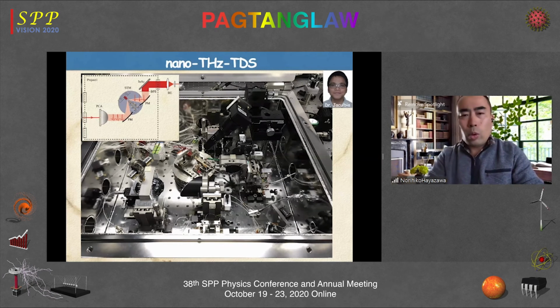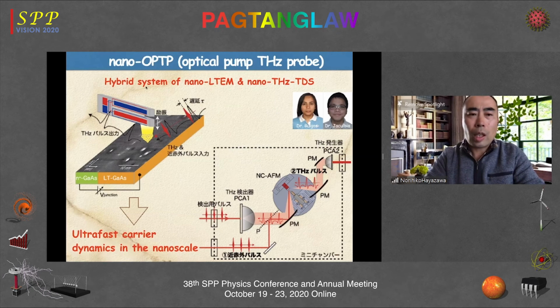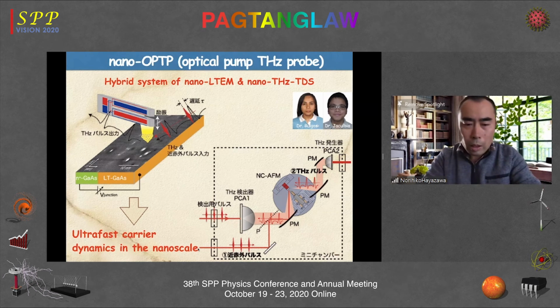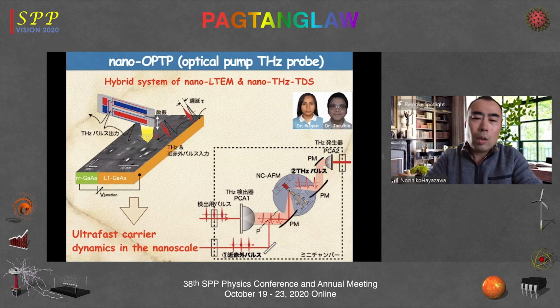And in fact, what we want to do is to combine these two systems. This is a kind of hybrid system of nano-LTEM and nano-terahertz time domain spectroscopy, called the nanoscale optical pump terahertz probe microscope. Briefly about this system, the near infrared laser pulse is introduced onto the SPM substrate junction to excite the photocarriers. After a certain controlled delay, the terahertz pulse is introduced onto the same position, the SPM substrate junction, to detect the carrier dynamics from the local volume underneath the tip. By using this system, we are expecting to characterize the ultra-fast carrier dynamics in the nanoscale in the future.